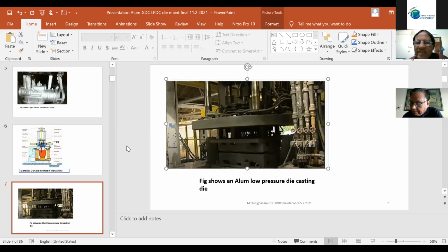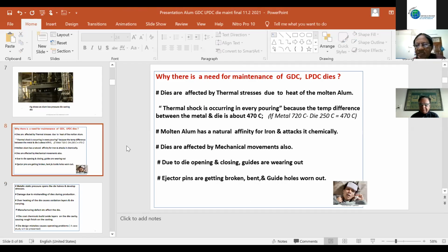Why is there a need for the maintenance of GDC and LPDC dies? Dies are affected by thermal stresses due to the heat of the molten metal. Thermal shock occurs in every pouring because the temperature difference between the metal and the die is about 470 degrees. Metal is at 720 degrees and the die is at 250. You are always pouring very cold water on your head and get a shiver. Like that, for every shot, the die is undergoing a thermal shock.